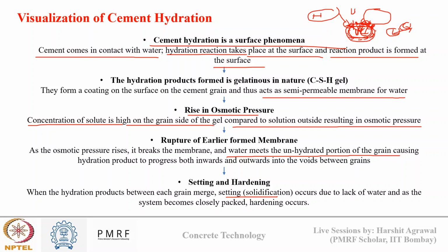That is known as solidification, or setting occurs because of lack of water. Now the water is occupied by hydrated cement grains, and as this system of cement paste becomes closely packed due to hydration, we say that hardening has occurred. Okay, so setting occurs when multiple grains merge with each other due to hydration, and hardening occurs when the system becomes closely packed, where it is able to take strength and bear a lot of load. Okay, so this is the process. From the surface, hydration starts, then osmotic pressure rises, then this semi-permeable membrane that is formed on the surface breaks, water moves inside, certain phases start to move outside and dissolve in the system, hydration deepens inside. Okay, and the binding of different cement grains starts to happen, and then the binding of the entire system happens.